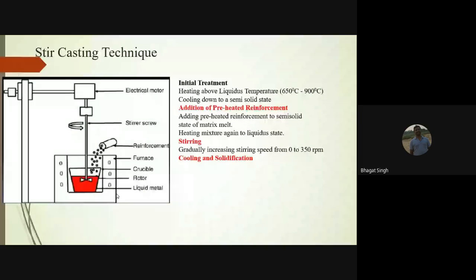So we have used the stir casting technique. Anyway, there are plenty of manufacturing methods available for the production of composites. In the powder metallurgy route, we can bypass the limits on alloying additions going into the solid solution, because if you are going with the casting method, then there are some limitations. By going with powder metallurgy, we can incorporate a lot of ceramic particles. But here we are using the stir casting method, which is very conventional and very effective for making aluminum-based metal matrix composites, especially when you are manufacturing very complex parts. This is the major advantage.